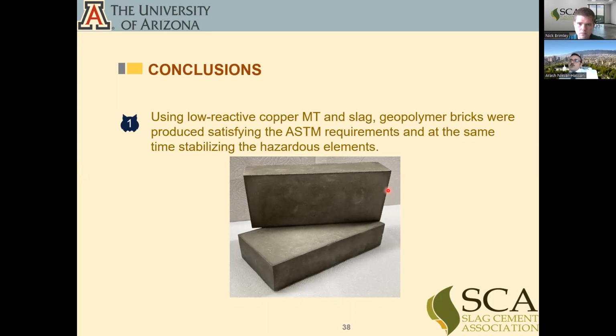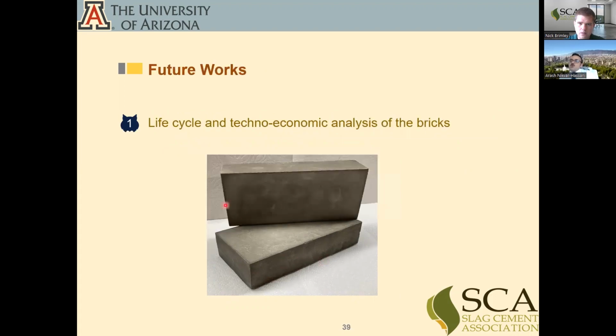So as a conclusion, we were able to produce bricks with the mine tailings and with the help of slag cement, passing all the ASTM criteria. The future work we need to do is a life cycle and techno-economic analysis on the bricks and see if we can economically produce these types of bricks.